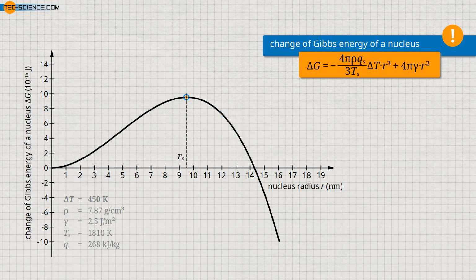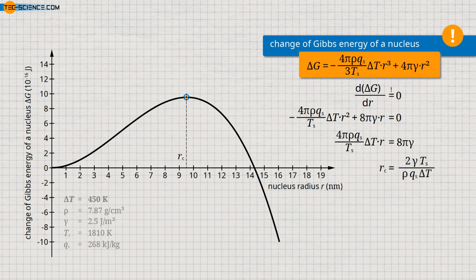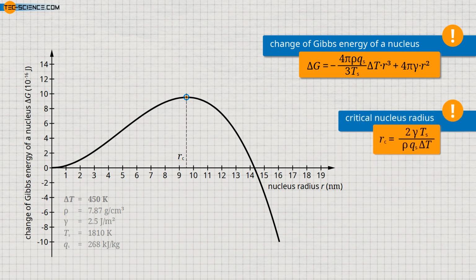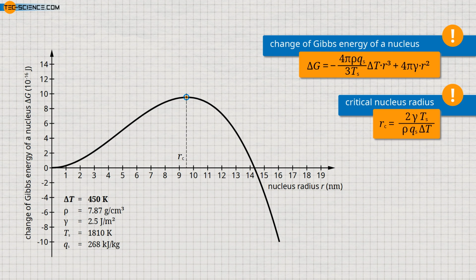The critical nucleus radius, above which a nucleus can grow stably, is obtained by determining the radius at which the Gibbs curve shows a maximum. By calculating the first derivative of the Gibbs function and setting it to 0, the critical nucleus radius can be determined. This results in the formula shown for the critical nucleus radius. Let us consider a small example at this point. The supercooling of metals during homogeneous nucleation is of the order of about 25% of the solidification temperature. For iron with a solidification temperature of 1810 Kelvin, for example, this means that supercooling of about 450 Kelvin is required for homogeneous nucleation.